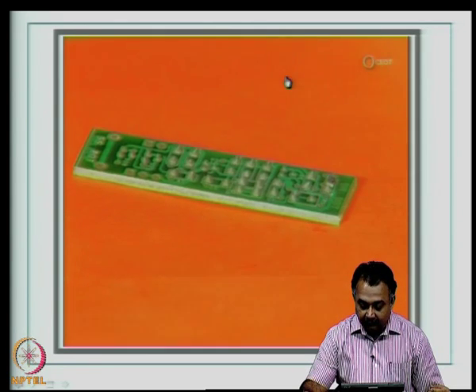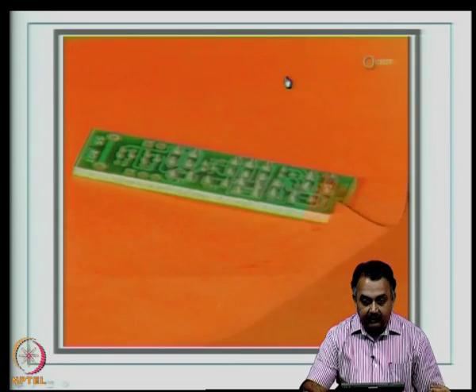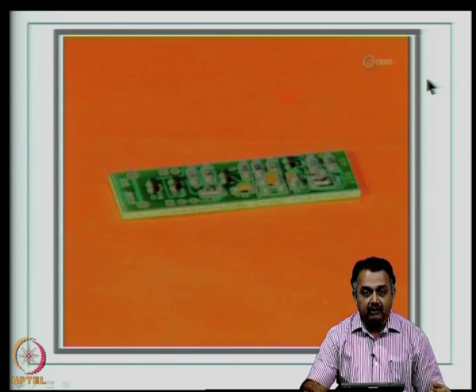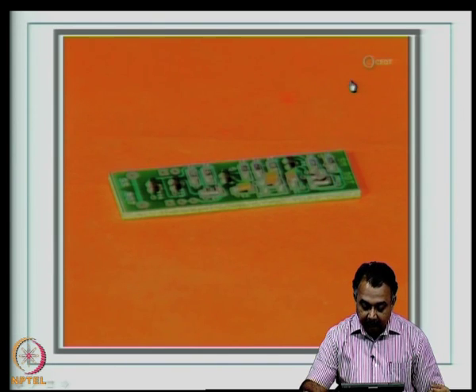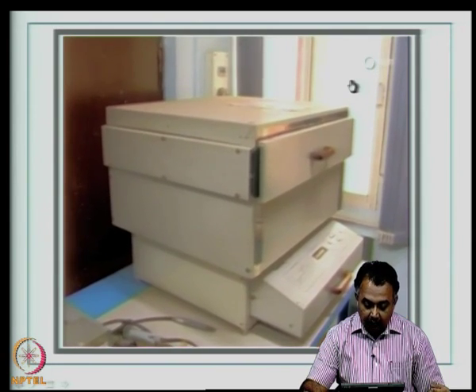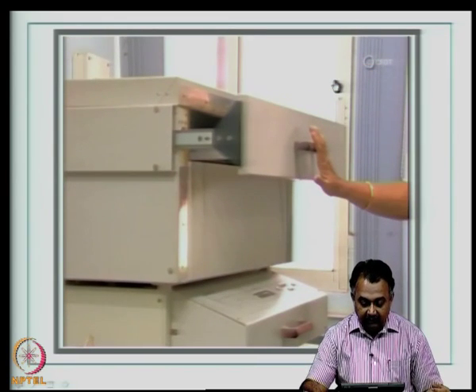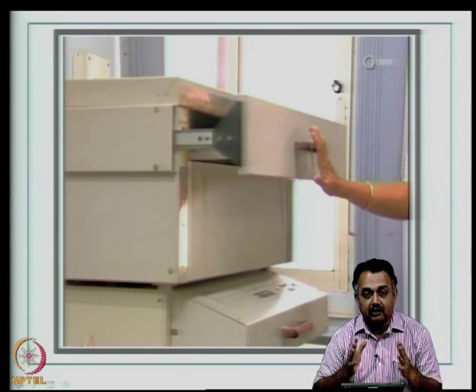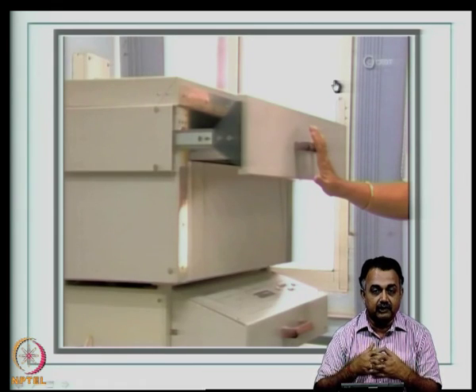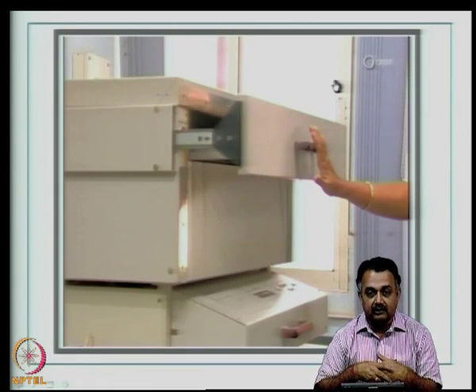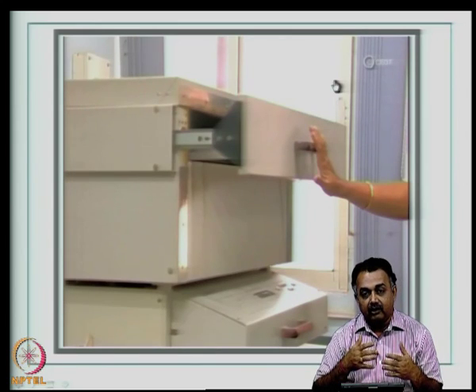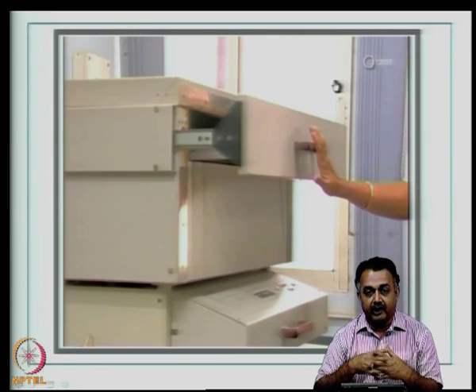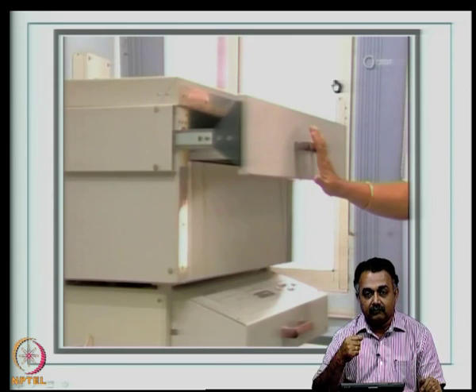This is a manual placement — tiny devices are placed on the solder paste. Here you can see a completely manually placed board on the dispensed solder paste. Now we move into a reflow oven. Before starting, you must create a temperature profile — understanding at what temperature the solder paste will melt, what is the glass transition temperature of the board, and whether any components can fail at the peak temperature. These three important criteria must be carefully noted before the reflow soldering process.